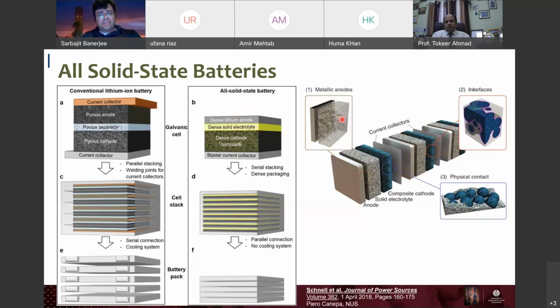Lots of challenges. The big challenge that has to be solved is to use lithium anodes. It is still incredibly difficult, because even though these are solid electrolytes, they still show lots of dendrite formation or mossy lithium formation at grain boundaries.